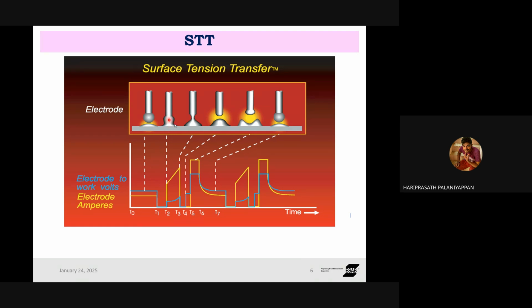During the interaction with the base metal, the current and the voltage both go to an off period. Then a ramp up period happens with the amperage and voltage too. During the ramp period, the ball detachment happens in the base metal, and after the necking happens, they again suddenly control the current and voltage waveform to the off period. With that off period, the complete detachment happens without any spatter formation. So we can say it's a spatter free process, about 90% control of spatter compared to the conventional GMAW process.